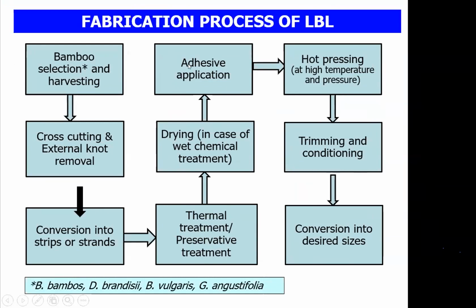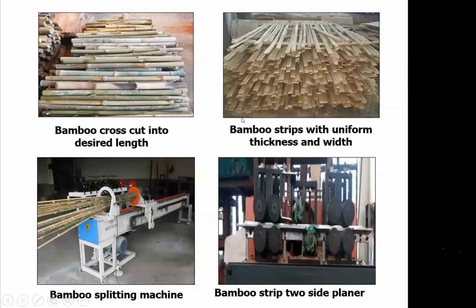And then drying, if it is wet we have to dry it, and then adhesive. We have to apply the adhesive on the bamboo strip surface or crushed bamboo strands. And then it should be hot pressed at high temperature and pressure. And then finally we have to trim and condition and then convert to the desired sizes. These are the different steps which can be used for converting the bamboo into composites.